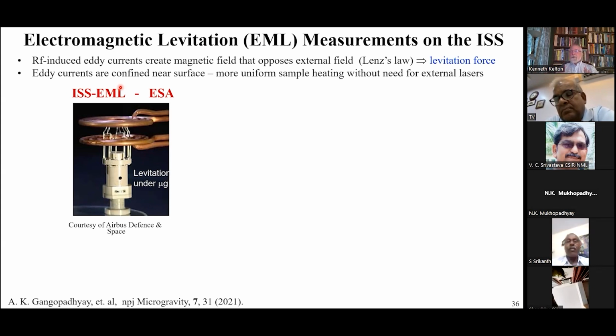If you do these experiments on Earth, however, you generally have one coil, and you have a problem because you always have to supply enough power to keep the sample levitated, in which case it's very difficult to cool the sample. But in space, you don't have that problem. This particular facility has two separate coils. One is a quadrupolar coil, and that's used for positioning. And one is a dipolar coil, and that's used for heating. And you can decouple those two.